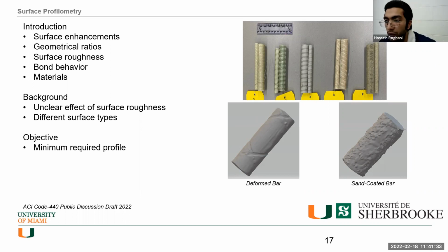strength. Because we have different surface enhancements, we should use different factors for each of them. But if we can correlate all of these surface enhancements to a parameter, the surface roughness, we can say that you do not need to just go to the code and check if it's the sand coated, is it the deformed, is it the grooved one, what is the type, and come up with the bond behavior. You can just use the surface roughness and characterize all of your surface enhancements. But now it is unclear how the surface roughness can affect the bond behavior in reinforced concrete structures. In addition, having different surface types doesn't let us work with the same KB factor for all rebars that has a minimum required characteristics that can satisfy the desired bond behavior.